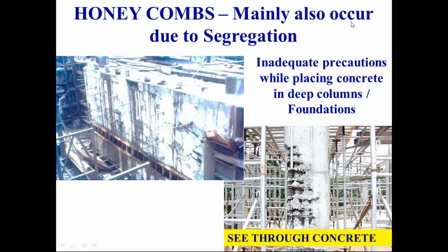Here you can see after the formwork is removed, you are in for a surprise. The arrows show on one side honeycombs and on the other side massive voids. We can call them rat holes, or it is like looking at footsteps of the father of the nation. He couldn't have gone into the concrete and made these footsteps. So segregation due to improper placing is a very important aspect, which we rarely supervise. Rarely do people supervise the placement, and they are not very particular about segregation. Then you get concrete like this. Next.